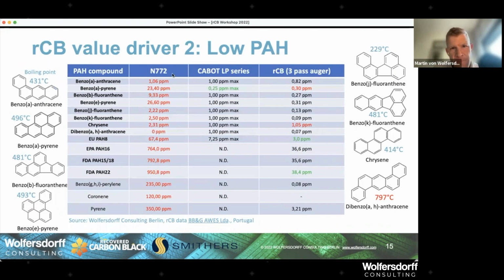Just to say, furnace carbon black, and typically the furnace carbon black that is replaced by recovered carbon black, has a very high content of polycyclic aromatic hydrocarbons. There are low PAH carbon blacks like this one, the Cabot LP series, but they are easily 500 euros per ton more expensive than the normal carbon black. And then when we look at recovered carbon black, this is recovered carbon black from a client in Portugal. We can see if you do things right, you have a very, very low content of PAH.